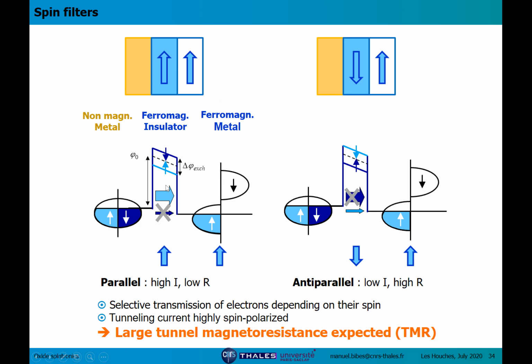In this case, for instance, the spin up electrons have a much higher current, because the barrier height for spin up is lower than for spin down. And here, if you have a ferromagnetic half metal as the counter electrode, you will have a large current. In this case, you will have a large current in principle for the spin down, but they cannot tunnel into the half metal here.